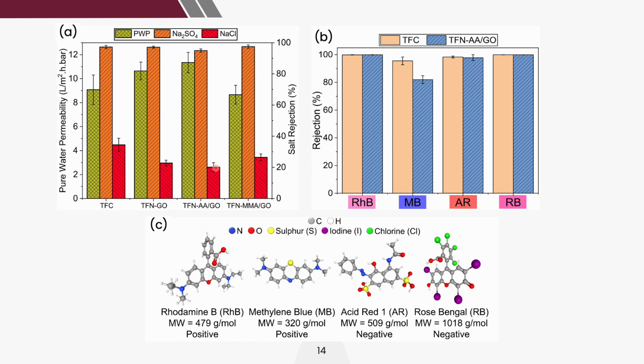remember, in the early part of my presentation, we actually want to achieve a high saline recovery rate. It means that we need the membrane to have as low an NaCl rejection as possible. For the salt rejections, we actually don't really care about it, because the lower the better. For the dye filtration, you can see that most of the membranes are able to reject the dye perfectly, except for the methylene blue, because this pigment has the lowest molecular weight.